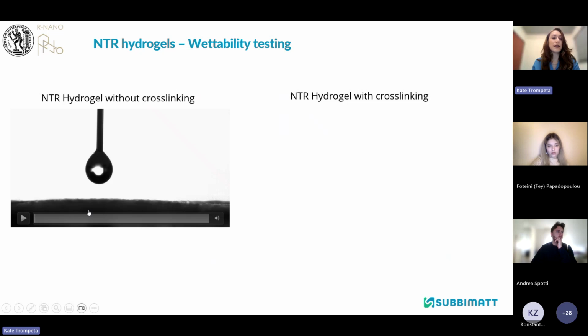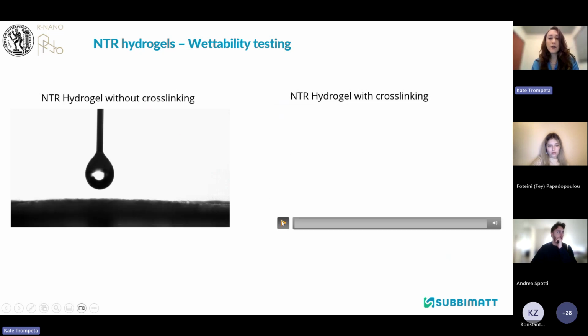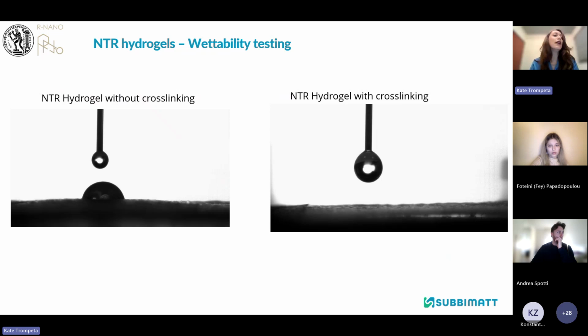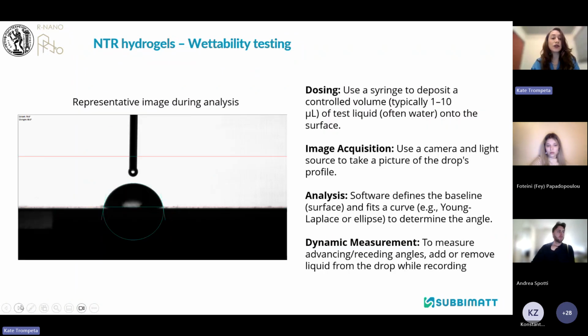So here you may see real testing when trying to make contact angle measurements. In both cases, we have applied an NTR hydrogel that can be synthesized in the lab. On the fabric, it's the same fabric piece in both cases. In the first case, however, we have not cross-linked the material, the hydrogel. While in the second case, there is a cross-linking between the hydrogel and the fabric. So you may see that we have differences in the wettability. And we do not study only this type of phenomenon, but we are also trying to determine differences between the reference fabrics. So what is the procedure of the wettability testing?